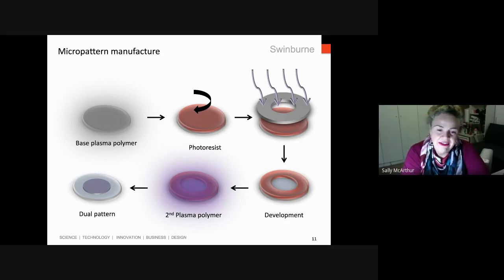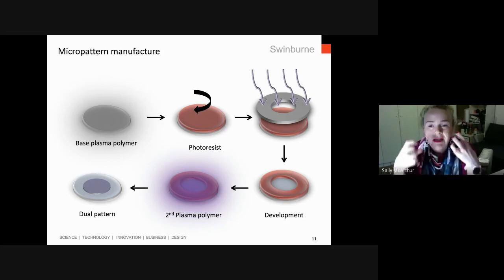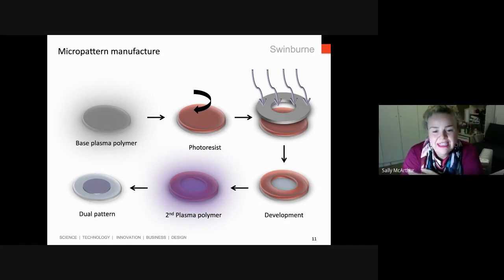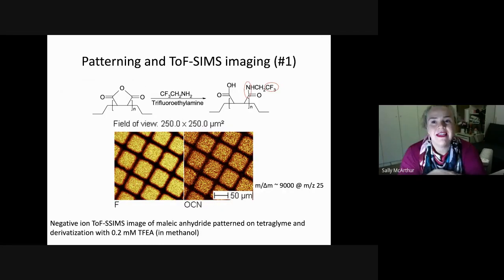Now, one of the interesting things when we set out to do this was that I was pretty sure that the resist process was going to either remove, damage, or significantly challenge our plasma polymers, remembering that we're not making technology-hard, rigid, heavily, densely cross-linked plasma polymers. We're making quite soft ones with actually quite high functional group retention, and we're actually interested in the properties of those functional groups. But the interesting thing to come back and look at, and now I introduce a little bit of TOF-SIMS to the picture, is we can pattern that anhydride chemistry.